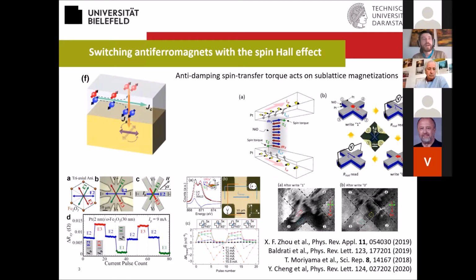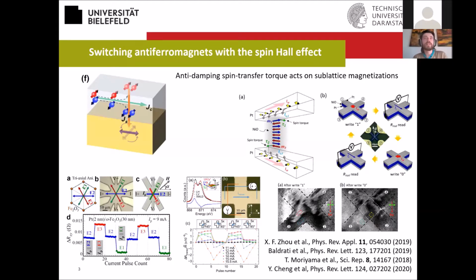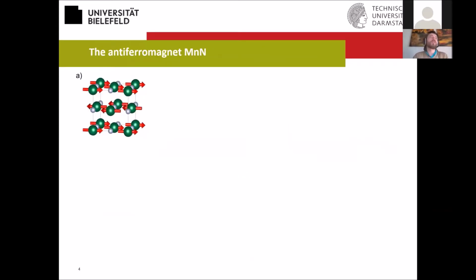I'm just bringing up some examples of switching experiments where the antiferromagnetic order has been manipulated with the spin Hall effect, basically due to the anti-damping spin transfer torque originating from the spin current that is injected into the antiferromagnet. And that allows you to manipulate the Néel order in antiferromagnets. So we looked into whether we can switch a metallic antiferromagnet, because all the other experiments that I've shown you have been done on